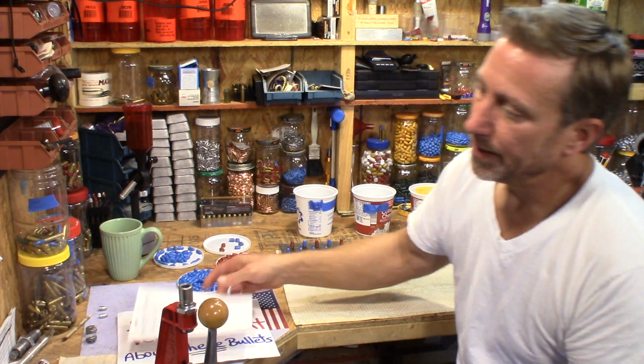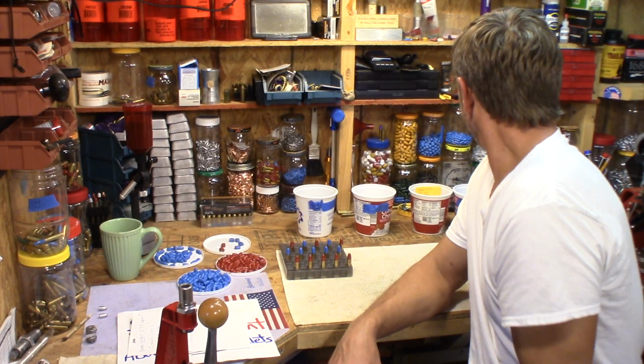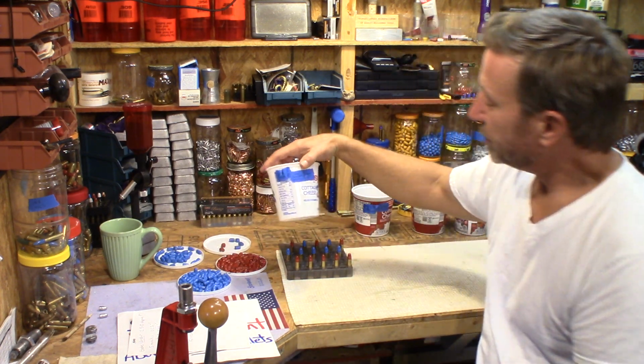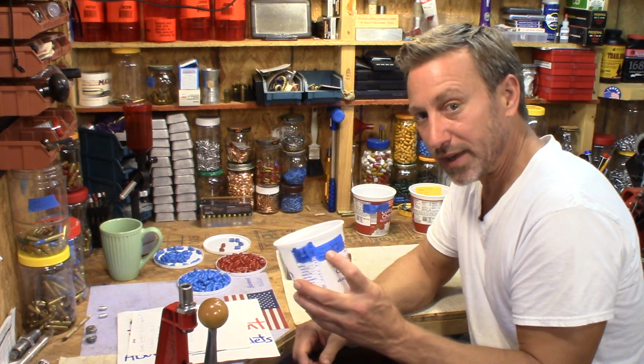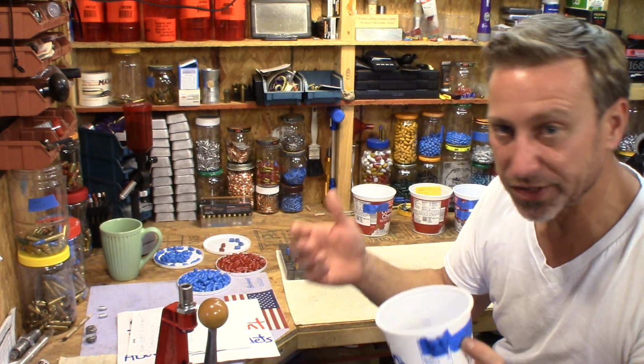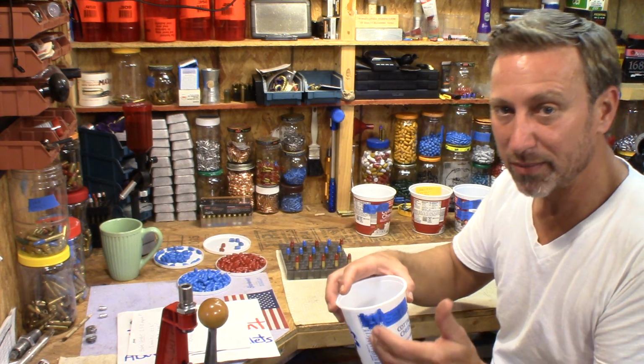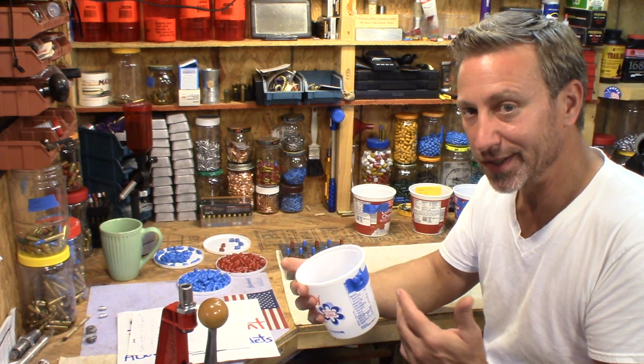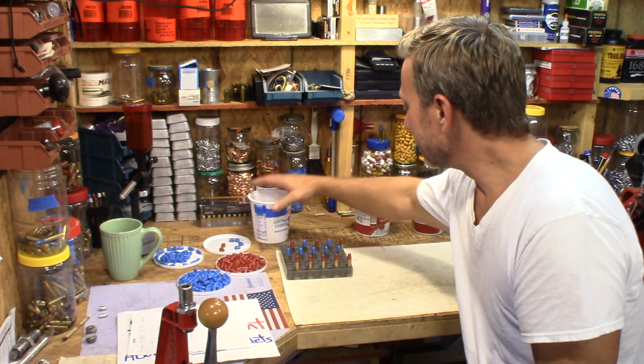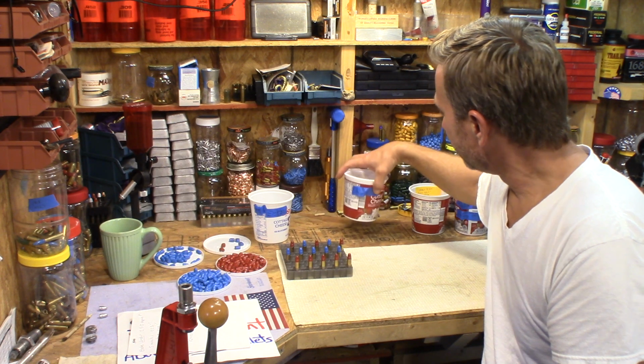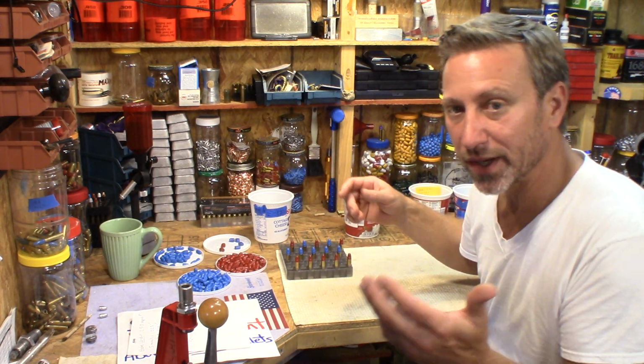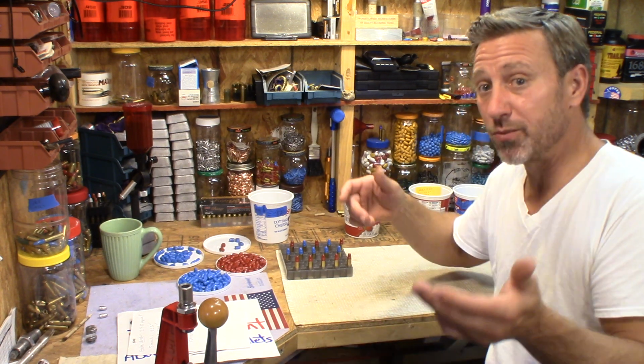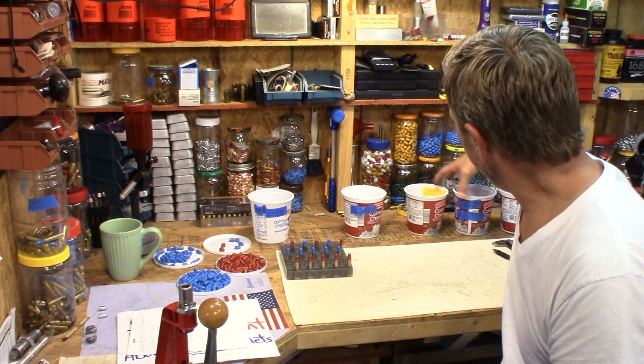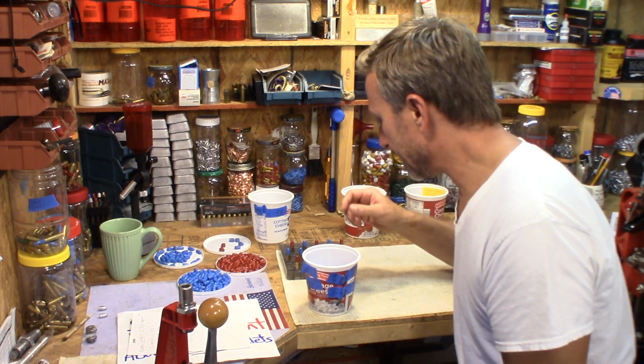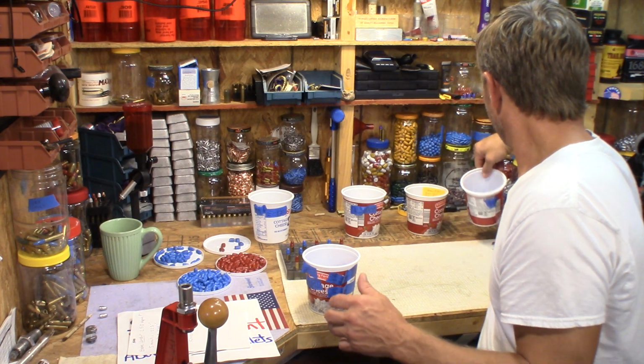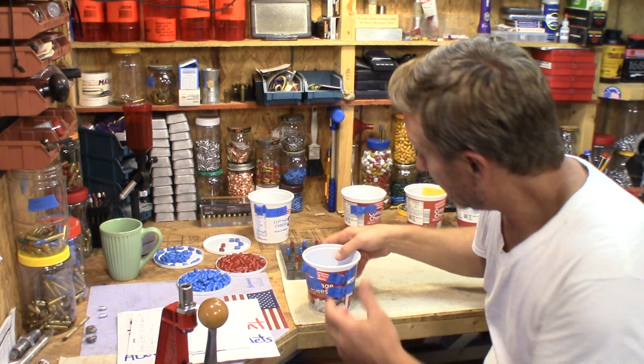So now, let's see. Okay. I told you I baked the same bullets from the same batch at 400 degrees for 20 minutes, and my BHN was like 11 or 12. It may be a little bit higher right now. It may eventually work its way up to 14, 15, 16, somewhere in that area. But the batch that I did, let's say, okay, oh yeah.